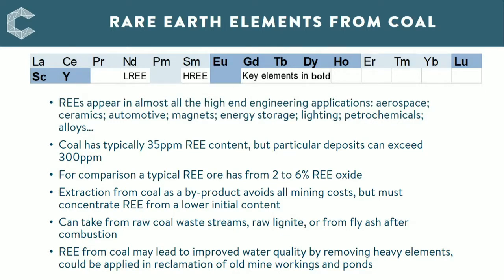For younger coals like lignite, the rare earth content tends to be associated with the organic fraction of coal, and I had expected that to mean it would be preferable to extract the rare earths from the fly ash, where there is a concentration of the metals. However, the researchers are finding that it's easier to obtain the rare earths from the weakly bonded carbon compounds rather than after combustion, where they're fused into an aluminosilicate glass.